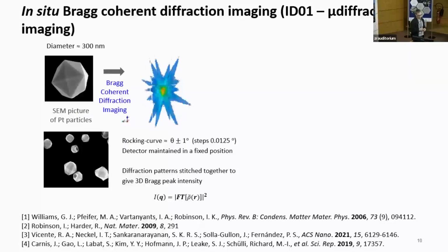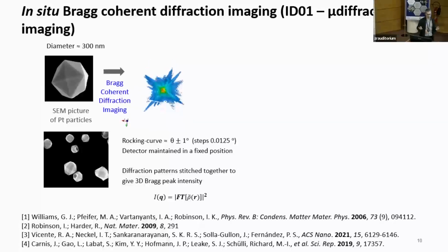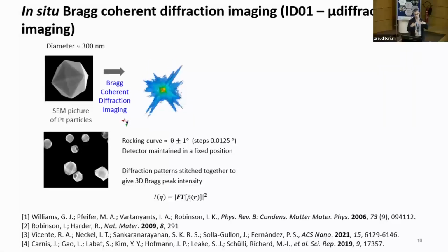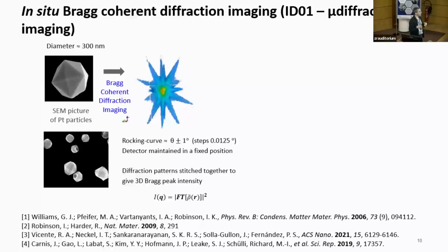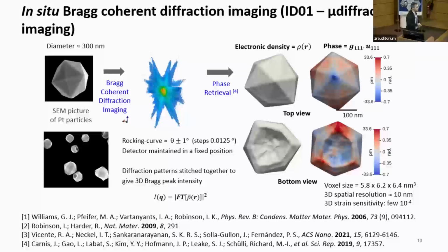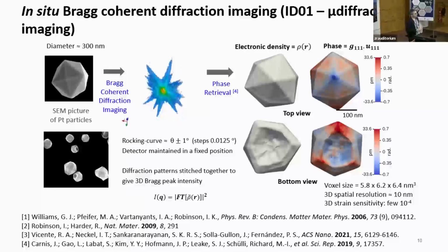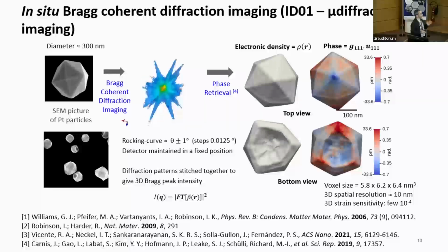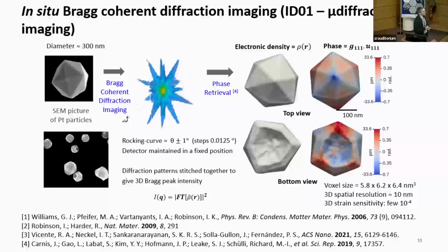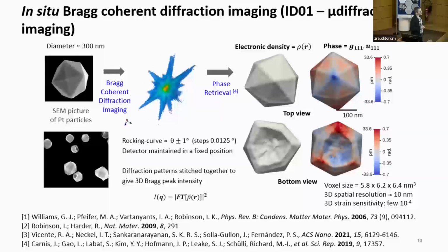intensity. So since in a real crystal, the atoms are slightly out of their equilibrium position, essentially the structure factor is a complex number. So it means that from this complex number, you can extract the amplitude to get insight into the morphology of the particle. And you can use also the phase, the projection of the atomic displacement onto the scattering vector. And there you can get insight into the strain distribution.